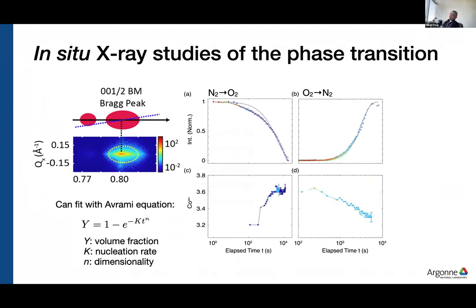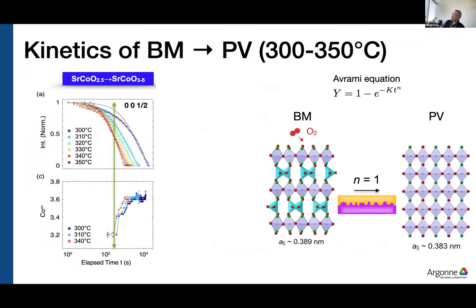And so we could analyze this phase transition with the Avrami equation, which I'm showing in the lower left. So Y is the volume fraction, K is the nucleation rate, and N is the dimensionality of the transition. And so the dashed line shows the fit to the Avrami equation. And when we switch from the Brownmillerite to the perovskite phase, we get a dimensionality of one, okay? N is equal to one for this transition. And so that suggests that it's a 1D transition, presumably from the top, okay?